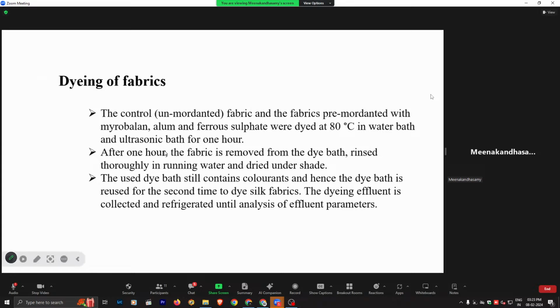Dyeing process. First, I chose unmordanted fabric and pre-mordanted fabric. The fabrics pre-mordanted with myrobalan, alum, and ferrous sulfate were dyed at 80 degrees Celsius in a water bath and ultrasonic bath for 1 hour. After 1 hour, the fabric is removed from the dye bath, rinsed thoroughly in running water and dried under shade.